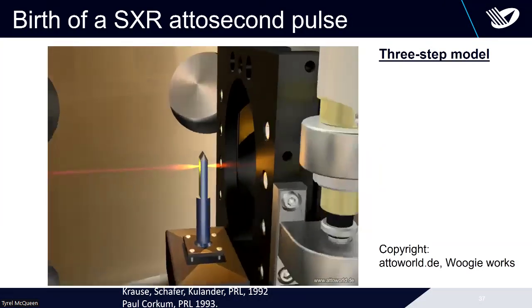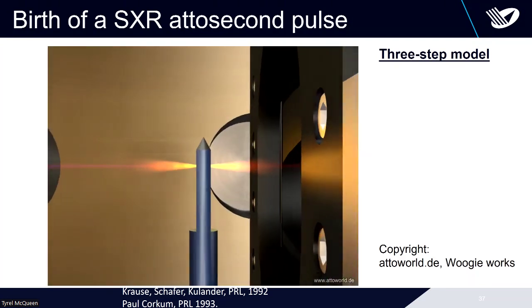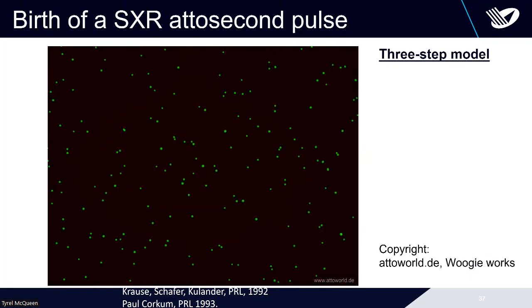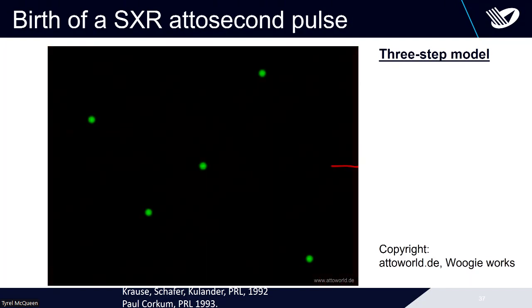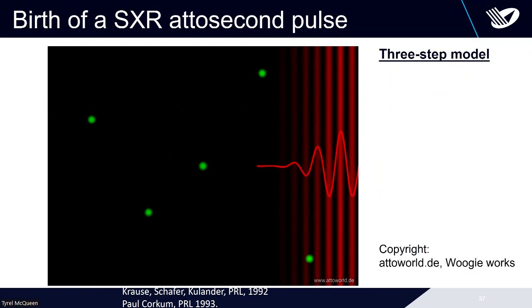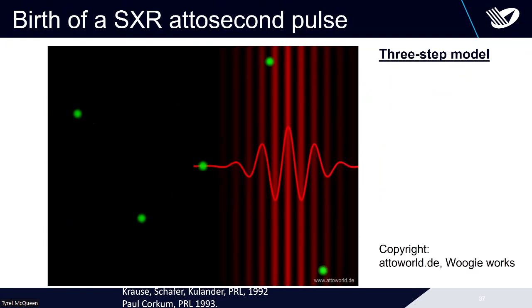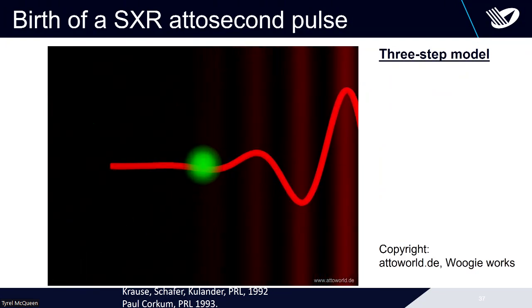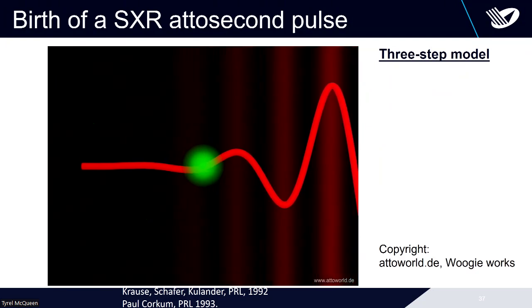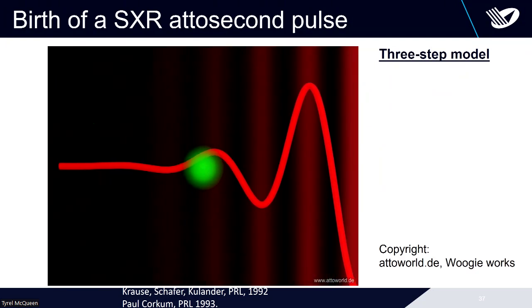So this is our gas expansion. The gas comes out to both sides. The little green dots are our noble gas atoms, say argon or neon. Helium is also used, and that's our ultrafast laser pulse: an oscillating electric field under a Gaussian envelope, the full width at half maximum of which is the pulse duration.